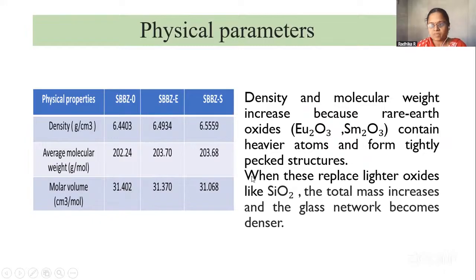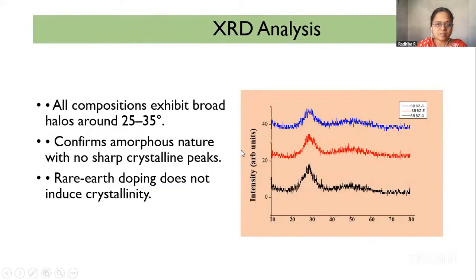And this is the XRD diffraction pattern for my synthesized samples. This one is the undoped glass sample, the second one is doped with europium, and this is doped with samarium. By observing this analysis, all the compositions exhibit broad humps between 25 to 35 degrees, which confirms the amorphous nature of the samples. There are no sharp peaks in the pattern, so the rare earth doping does not induce crystallization.